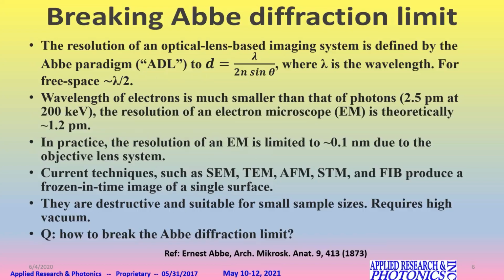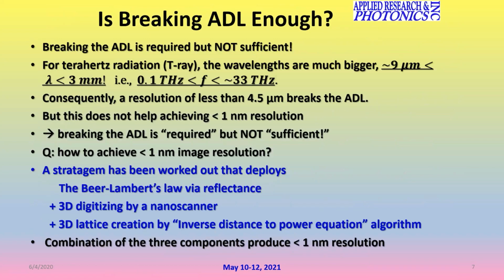But upfront, let me mention that overcoming the Abbe diffraction limit is necessary, but it is not sufficient to get to lattice resolution, because roughly 9 micron to 3 millimeter is the range for terahertz or T-ray wavelengths. So even less than half of 9 micrometer resolution is achieved by a lens system. It is nowhere close to lattice resolution, which is on the scale of angstroms. So what needs to be done? It needs to be overcome.